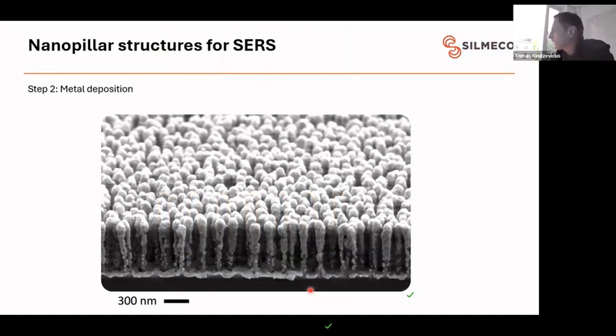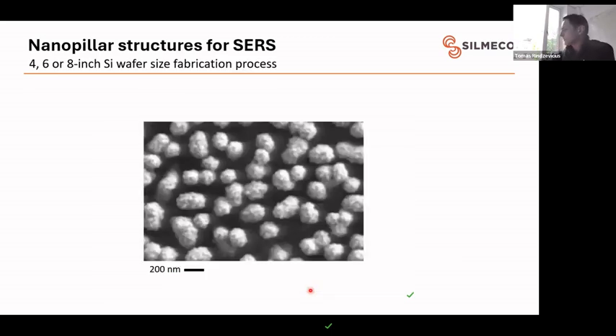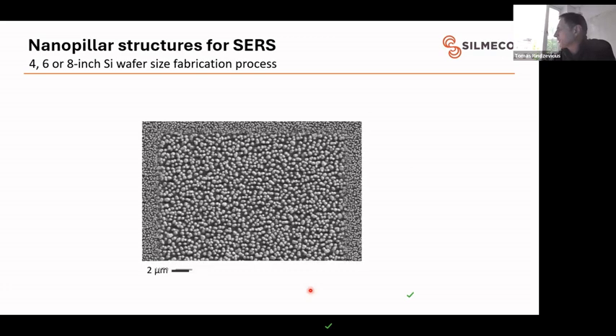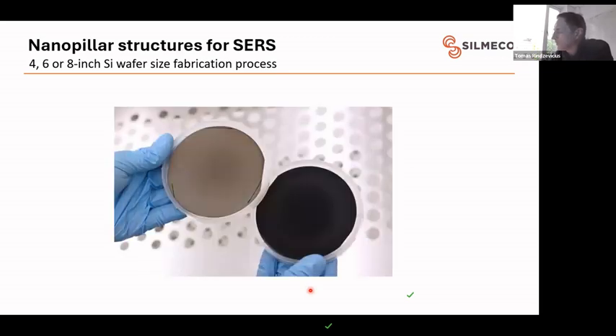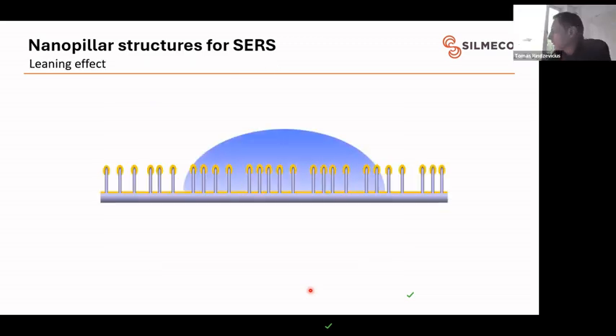And in the simplest form, the first structures that we fabricated look like this. They look more like pillars. And I believe this was not evaporation, but sputtering, that creates more like columns, so more uniform coating. But because they are so dense, they're not very uniformly coated. And if you look from the top, the structures, at least at some reasonable scale, look rather uniform. And currently we work on 4, 6-inch, and even 8-inch wafer sizes, mostly on 6-inch, but 8-inch is also possible.